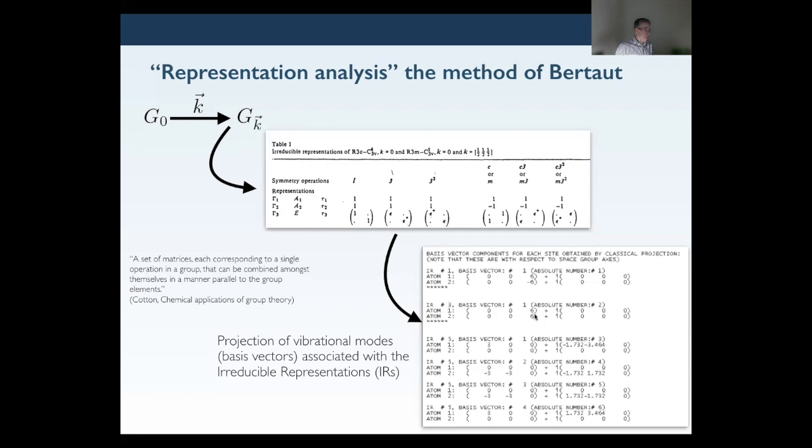So if we have ferro the same size in this one and antiferro the same size in this one, here we have to have everything else that's possible in the AB plane. There are no components along the C direction here, because if you combine irreducible representation 1 and irreducible representation 3, you're combining a ferromagnetic array with an antiferromagnetic array. So combinations of that will lead to components along C of all differing sizes. So the components along C are already covered by the first 2 irreducible representations. Number 5, you can imagine, is everything else happening in the AB plane.